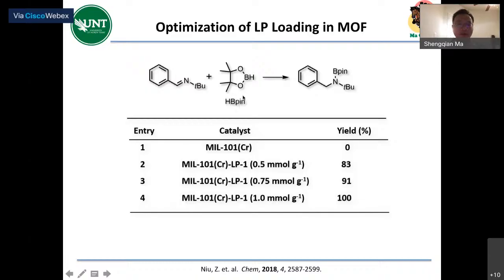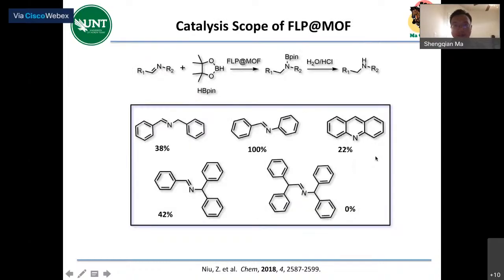So it uses boron hydride, pinacol borane, to do this imine reduction, to optimize the reaction. And then we expanded the substrate scope, and we found they can fully catalyze this substrate, this imine compound. And when we enlarge the size, of course, easy to understand, this one is larger than the pore size of MIL-101. They cannot enter the cavity of the MOF, so there's no conversion. But for those three, we found that it's not actually very active.